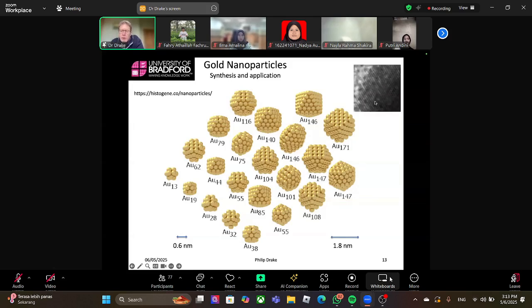If we zoom in on a particle surface, we've got good resolution. You can see these black lines. These black lines are the crystal lattice lines. So these lines are the same as the lines you see within a crystal. It's the lines of the atoms lined up. So when we can see lattice lines within TEM, it's a really nice thing to measure, to determine the kind of crystal structure you've got.